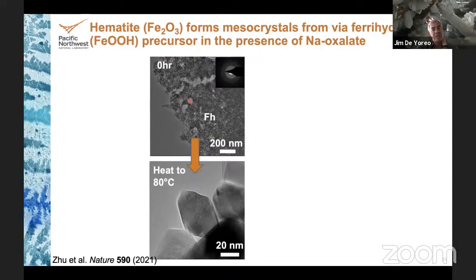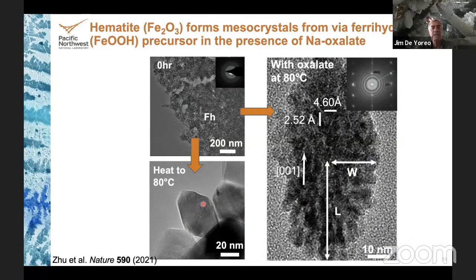Now, in pure water, if you heat this system of ferrihydrite, it will convert to beautiful single crystals of hematite that are rhombohedral in shape. If you put sodium oxalate into the system, oxalate acts like a ligand. The hematite particles never grow beyond about 5 nanometers, and instead you get these spindle-shaped particles where all of these domains have their 001 axis along the same direction. So the long axis of the spindle is along the 001 axis.